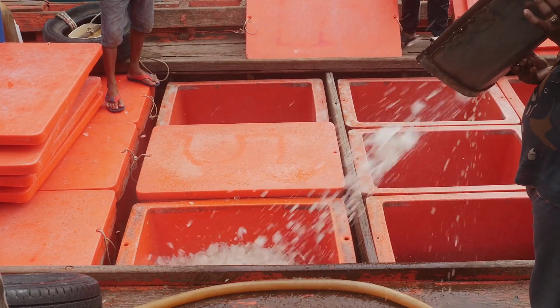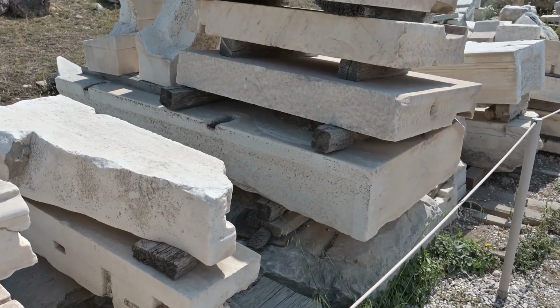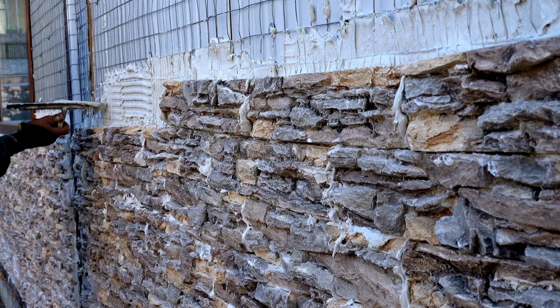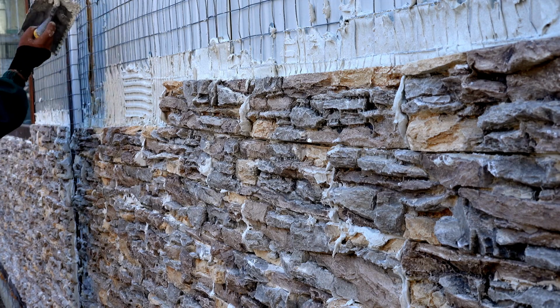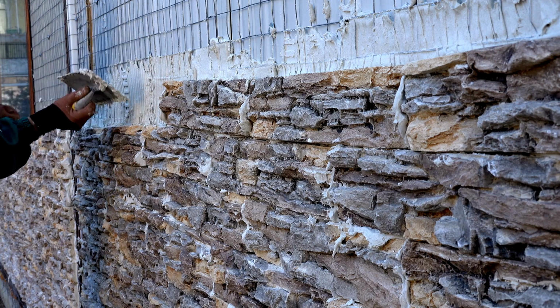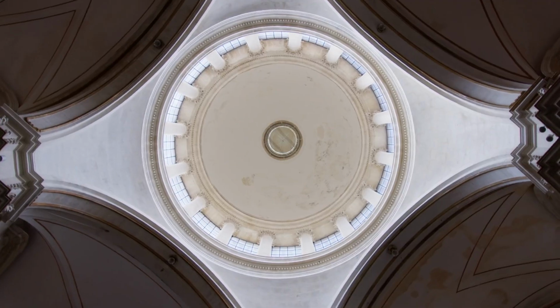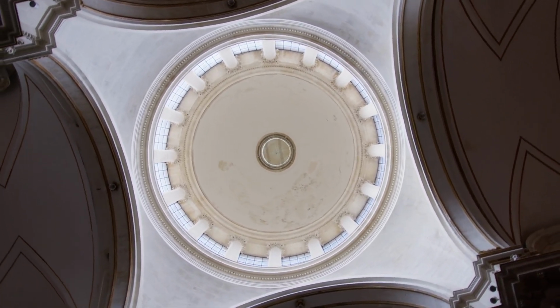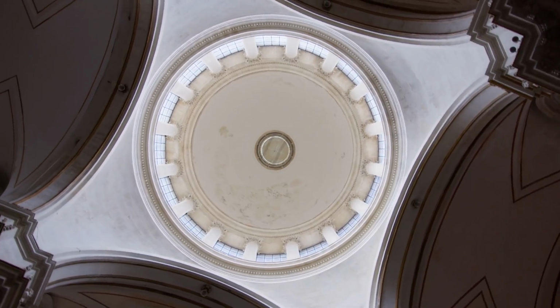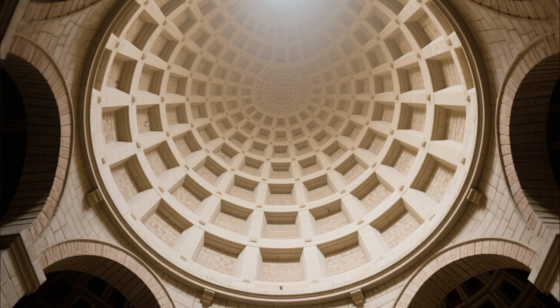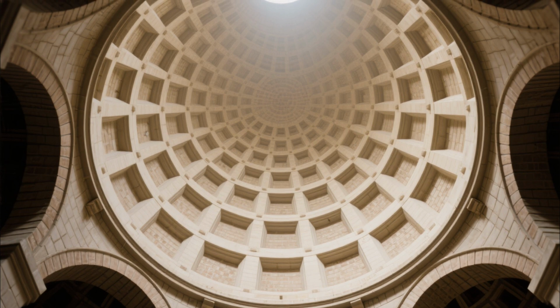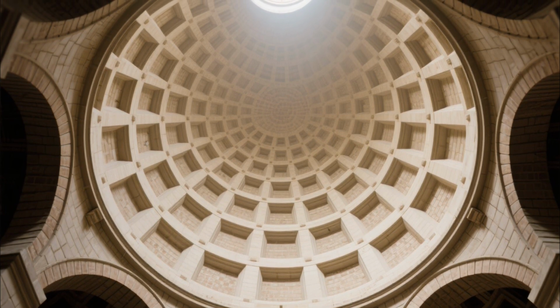rather than weakening it. The ingredients alone don't guarantee success. Placement and curing matter. Roman builders packed mixes with minimal bleed water, kept lifts shallow enough to ram thoroughly, and protected fresh placements from rapid drying. They also leaned on stonework to carry shape and stiffness, so the concrete didn't need to do every job by itself. Wall cores are a rubble and mortar composite where large stones carry load while mortar glues and redistributes stress. In domes and vaults, coffering and ring action mean loads flow around weak points rather than straight through them.